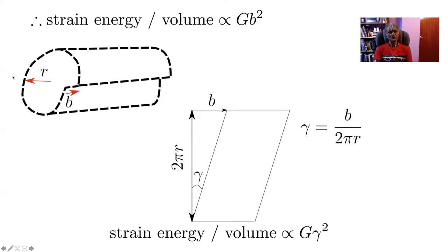So imagine we have a cylinder and we slice it halfway and we displace the two halves relative to each other so that they're still connected in this region but not here. And the magnitude of the displacement is the Burgers vector b. So if I unwrap this cylinder, then it will look something like this, where b is the magnitude of the displacement, and this is the height over which that displacement has happened, and therefore the shear strain gamma is b divided by 2 pi r. And as usual,